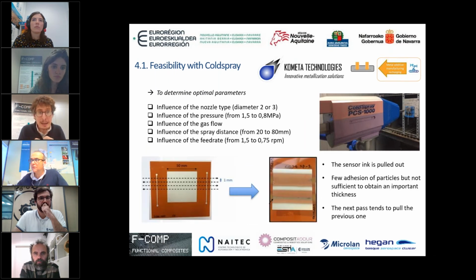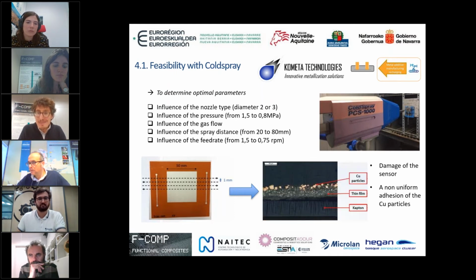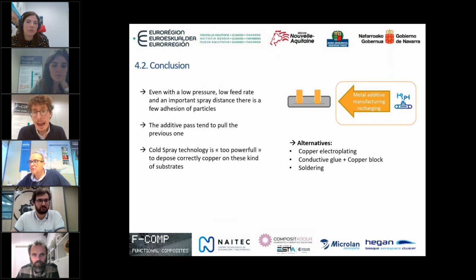Even after adjusting the type of nozzle, the pressure, and the gas flow, it was seen that very few particles could be made to adhere, because even when you pass one time and go back over it, you remove what you have put before. So we can say that we have a very non-uniform adhesion of the copper to the Kapton, and the sensor is damaged. Functionally speaking, this is not a valid solution for this application.